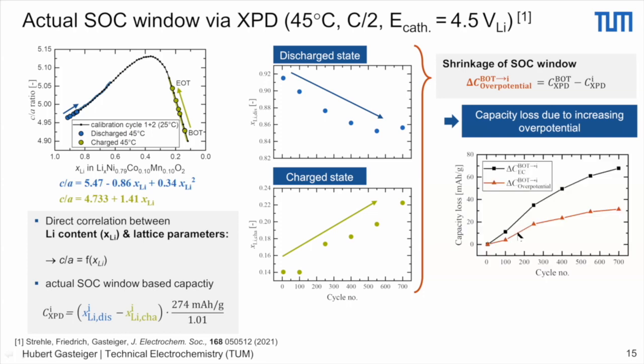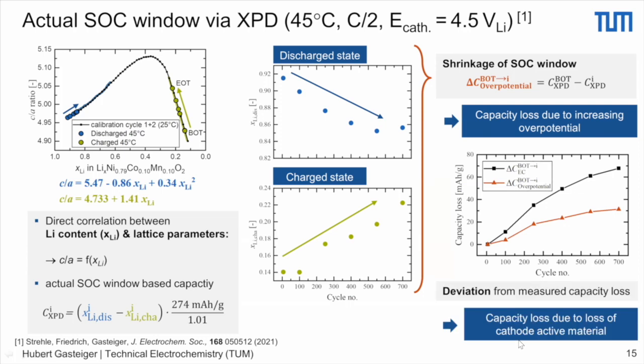So when we plot this, we can look at the capacity loss. Of course, first the one we measure simply electrochemically, that's this part here, and then the capacity loss which we would predict based on the shrinking SOC window detected by XRD, right? And so the difference between those two, of course, means that there must be a loss of cathode active material. And we will try, a few slides later, to quantify what this loss would be.